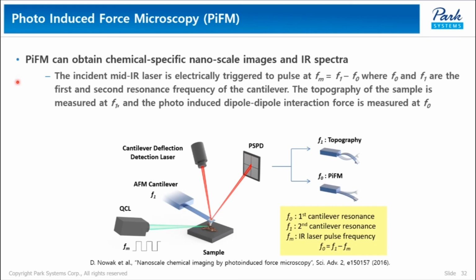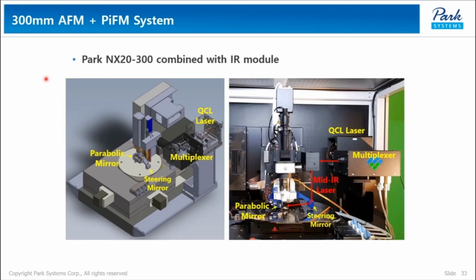Photo-induced force microscopy, PIFM, can obtain chemical-specific nanoscale images and IR spectra. The incident mid-IR laser is electrically triggered to pulse at fm, where fm = f1 - f0, F0 and F1 are the first and second resonance frequencies of the cantilever. The topography of the sample is measured at F1, and the photo-induced dipole-dipole interaction force is measured at F0. We have established an alpha system that can measure 300 mm wafer samples.